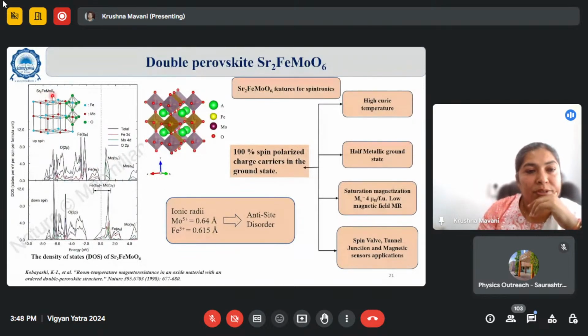Sr2FeMoO6 type of double perovskite, and you see there is no overlapping between this t2g Mo orbital and this Fe eg orbital. In such a case where there is no overlapping, it is generally the spin up channel, so it is creating a gap here. It is a semiconducting channel. There can be spin down states with overlapping of these two orbitals, t2g of Mo and Fe, and then it becomes metallic because there is no gap.